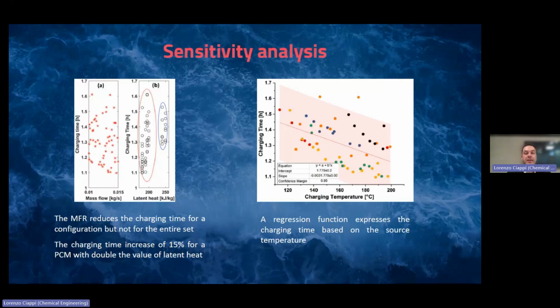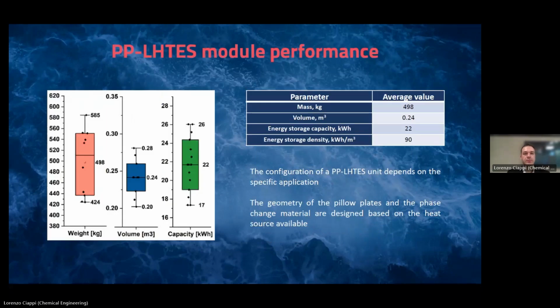Regarding the typology of the system of phase change material, so of latent heat, a doubling of the value of the latent heat determines an increase of about 15% for the charging time of the system. Moreover, a regression function was determined to link the charging time and the charging temperature, observing that an increase of the charging temperature reduces the charging time for the phase change.